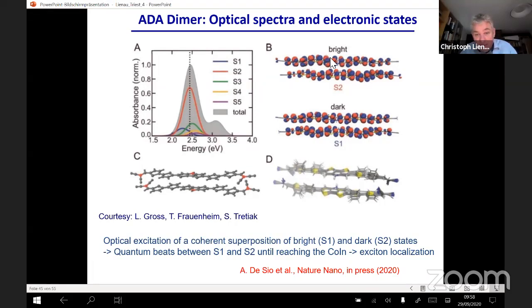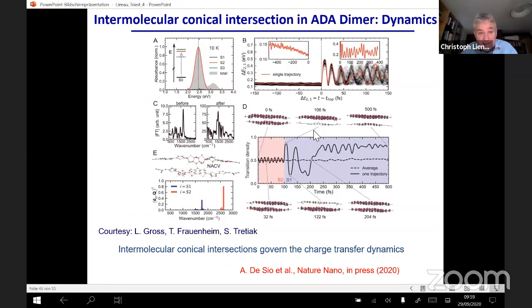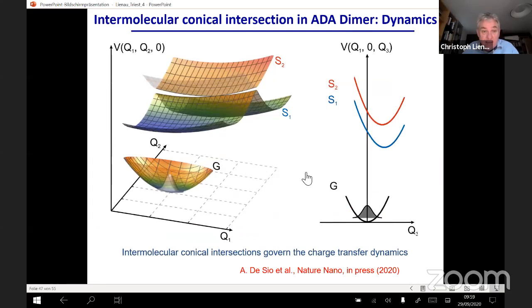You have seen that these two molecules order in a stacked form in some antiparallel ordering, and this gives rise to a bright S2 state. So the second excited electronic state is optically bright, whereas the lowest electronic state, the S1 state, is optically dark. Theory tells us that this state evolves for a few tens of femtoseconds on the optically bright surface, but then it jumps over, by non-adiabatic coupling induced by the coupling to a strong antisymmetric vibrational mode of the system, to the optically dark surface, and then afterwards oscillates on this surface.